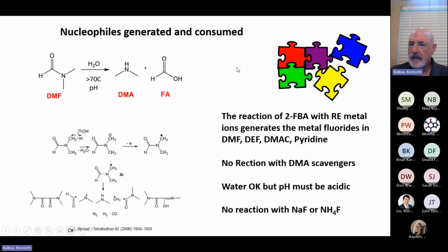Okay. We think that this is important. In fact, if we add a DMA scavenger to clean up the solvent, remove any DMA or formic acid, there's no reaction. So that's kind of important for this reaction. The presence of water seems to be okay, but it needs to be acidic. If we just throw in sodium fluoride or ammonium fluoride, we don't make these metal organic frameworks. It doesn't work.